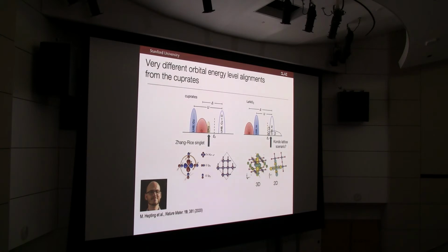Okay, so in the nickelate case, we have a similar but shifted landscape. By analogy, we have our upper and lower Hubbard bands of the nickel dx squared minus y squared levels, but it's quite a bit higher than the oxygen 2p band. And so this is interesting in two regards. One is that by hybridization, we still have something that looks like this. This is a Wannier projection of that kind of band. This is the big hole-like Fermi surface in Warren Pickett's calculation I showed earlier.